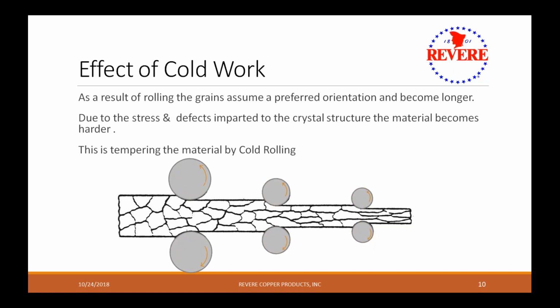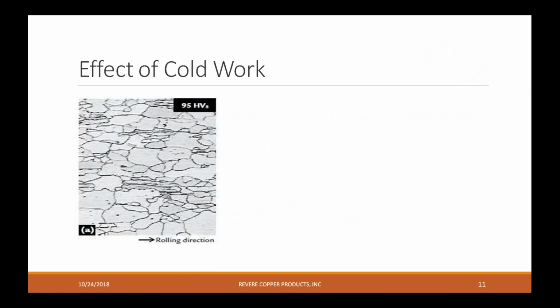So you can see when it's first going into that first set of rolls, the grains are big and they're non-directional. And then as you roll it, the grains get smaller and squished and elongated and they become directional. So I have a picture of what that would look like under a microscope. So that first picture more closely resembles that picture I showed earlier of the structure after it's been maybe cold rolled and annealed. So you've got good grains, good grain structure. You can see it. There's not a lot of directionality.